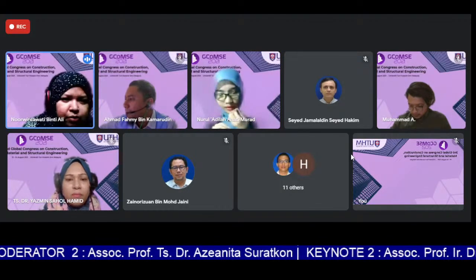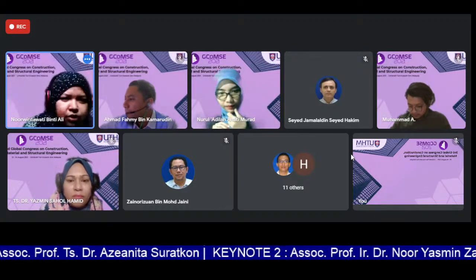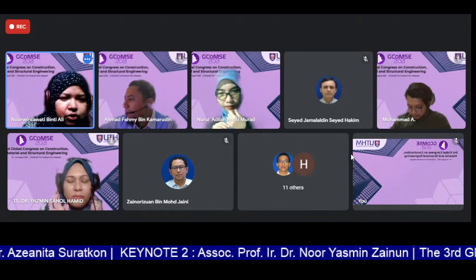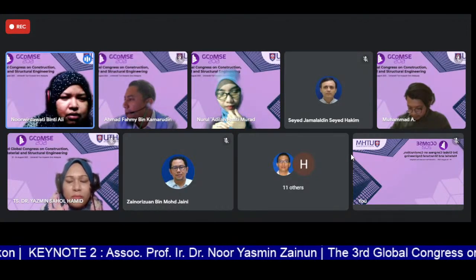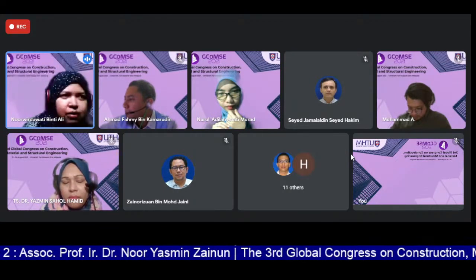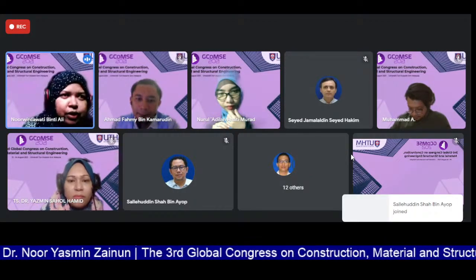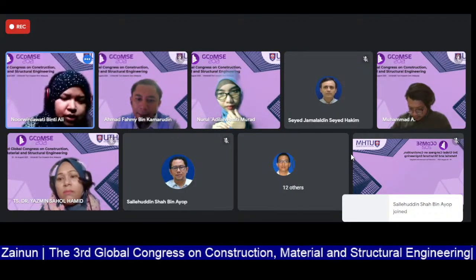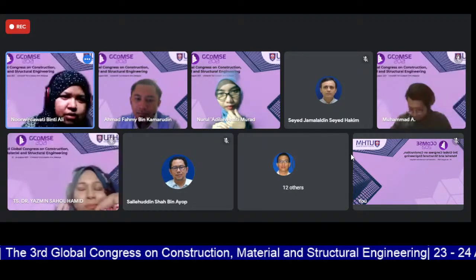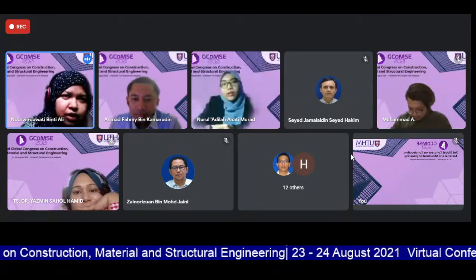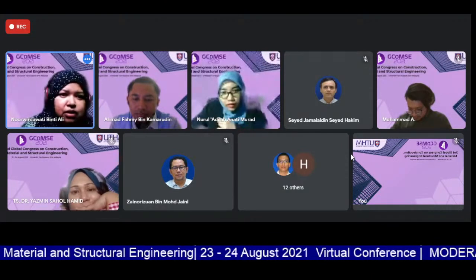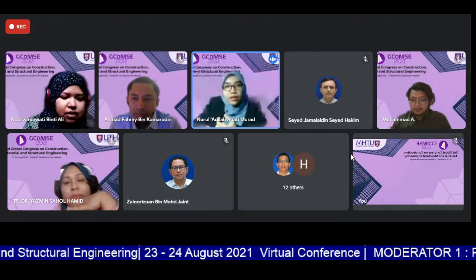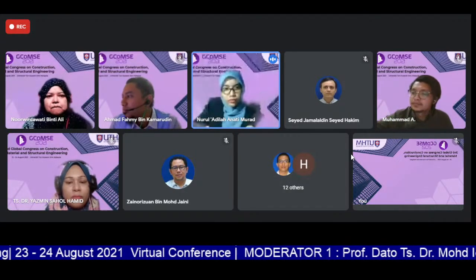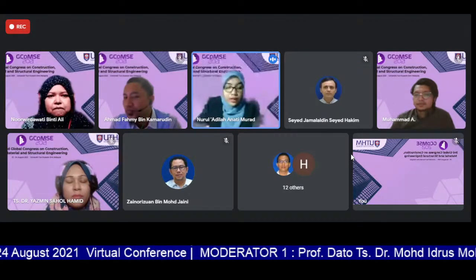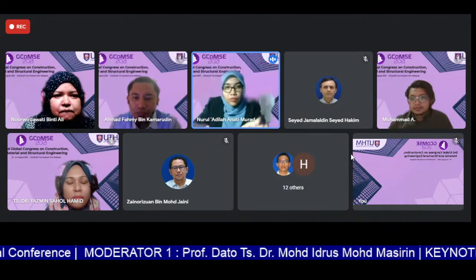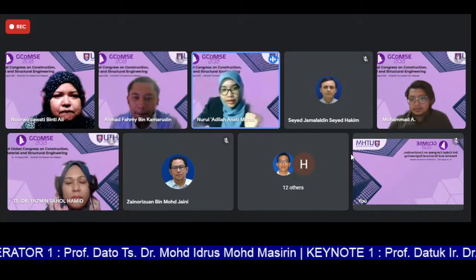Besides the cube test, for your specimens, the 2 mm, the 4 mm specimen, the column, do you observe any failure on the concrete? Can you see any failure on the concrete, or is the failure on the steel only? Yes, the failure is only on the steel. However, on the tube it shows failures, but just a small crack at the edge and at the sides of the tube.